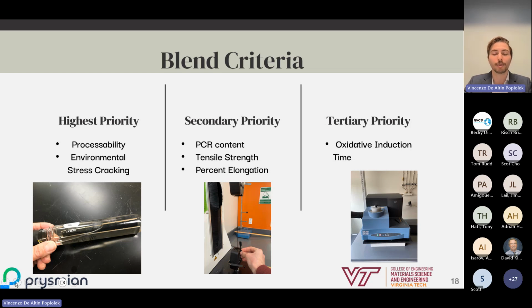Of secondary priority was PCR content, as while we wanted to increase this as much as possible, we had to make sure that we were still passing industry standards. Then tensile strength and percent elongation. While we still need to pass industry standards for these, it is not as common of a failure mechanism, and as such we did not feel a need to optimize much past that level. And then finally, our tertiary priority was oxidative induction time, as this is something that is the easiest to change, as we can add an antioxidant package and thus did not need to design around this.